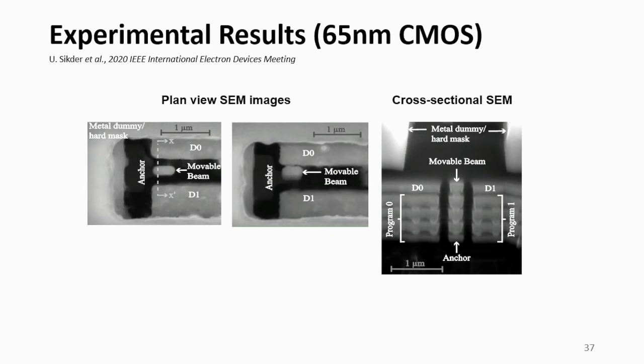Plan view SEMs on the left, showing the as fabricated switch, back end of line, single pole double throw switch, and then after it's actuated to be in contact with a data zero conductive electrode. And then shown on the right is the cross-sectional SEM showing multiple layers of metal patterned to form the movable beam. You have the actuation electrodes on the lower layers, and then the contact conductive electrodes in the upper layer.